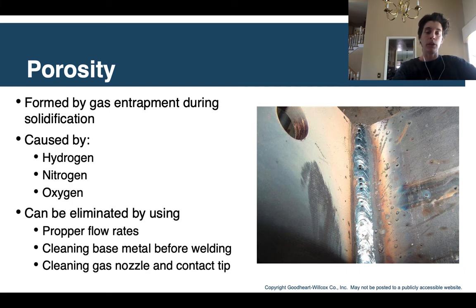The way that this can be addressed and eliminated is by having proper flow rates. So that would be adjusting your regulator. I mentioned that you don't want to go too high with the flow rate. That can cause problems as well as being too low. But that's the first thing you should check if you see a lot of porosity: check your flow rates. Also, cleaning the base metal before welding is going to be super helpful. If you're having a lot of problems, it could be oil left on the base metal, or it's super rusty or had paint on it, stuff like that. All those can cause porosity.